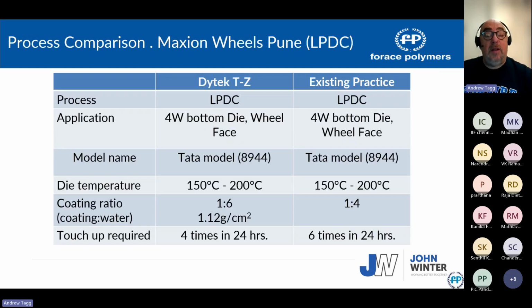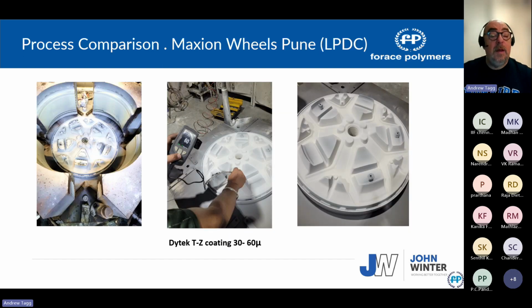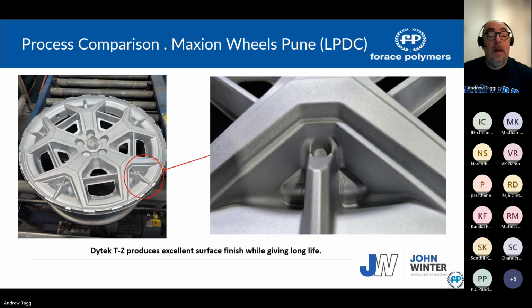Another one, this is Maxion, this is LPDC, where this is the TZ. We use the TZ more for low pressure wheels, and it's a bottom die face again, and you'll see the pictures here. So there's the bottom die face, coated, and you can see the surface finish. I enlarged that of the wheel, a very high requirement for surface finish for these wheels.